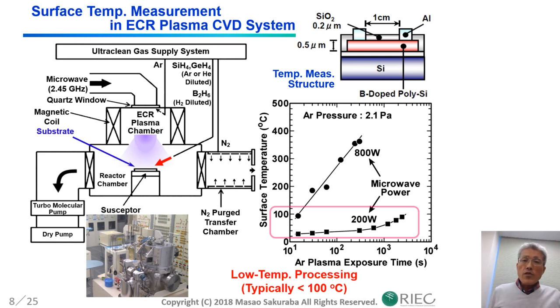By using a temperature monitor device, we have confirmed the average temperature of the substrate surface region. The surface temperature tends to rise with higher power microwave and longer time irradiation. But by employing lower microwave power, it has been clarified that we can keep the surface temperature below 100 degrees C.